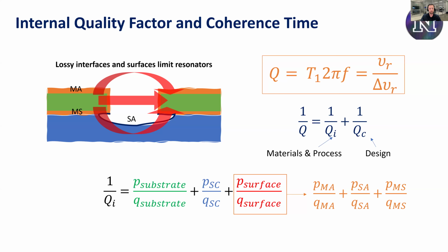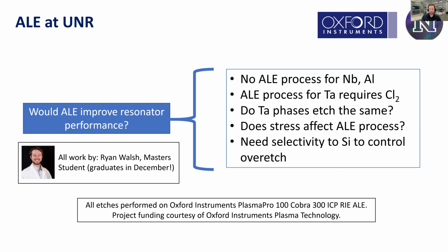I'm going to move a little quicker than I normally do just because I think I'm so used to giving hour-long talks, and this is supposed to be 45 minutes. Well, we're really interested in whether we can use ALE to improve resonator performance. There's no ALE process for niobium and aluminum, which are two of the very, very common materials. There is previously published, I believe by Lamb, an ALE process for tantalum, but it requires chlorine, and it was not really done specifically for the qubit community.